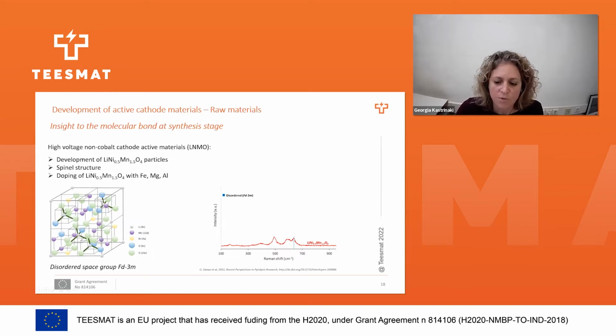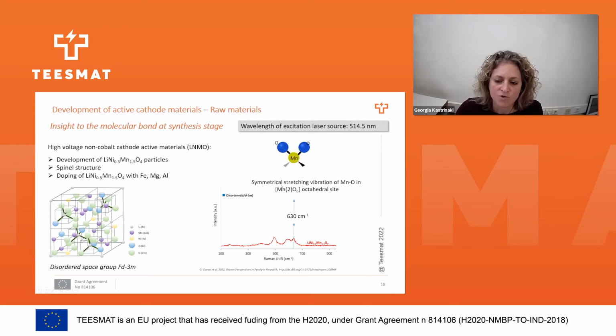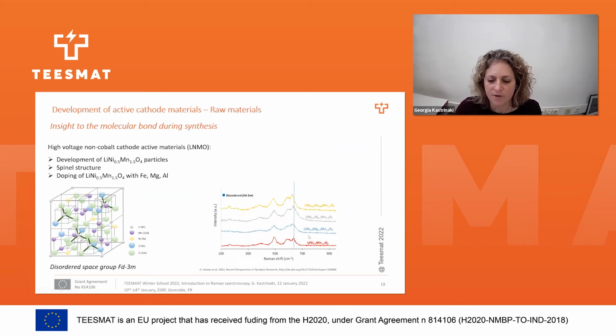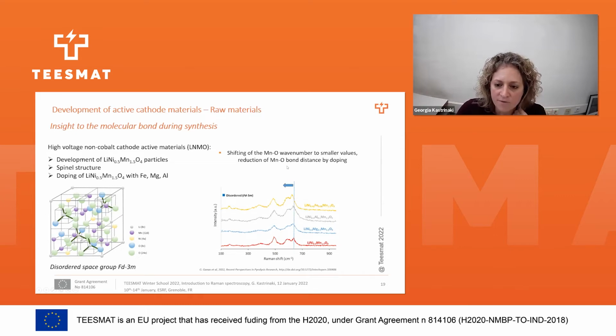And this is a typical spectrum of the LNMO of this disordered structure. We will focus specifically on this peak here, which is at 630, and it's attributed to the symmetrical stretching vibration of manganese and oxygen in these manganese oxide octahedral sites. So here you can see the different Raman spectra that we got for the different kinds of materials, where we actually tried to substitute nickel in our structure with iron, aluminum, and magnesium. And you can see that we have a shifting to lower wave numbers of this specific bond. And this can be related actually to the bond distance of this molecular bond.